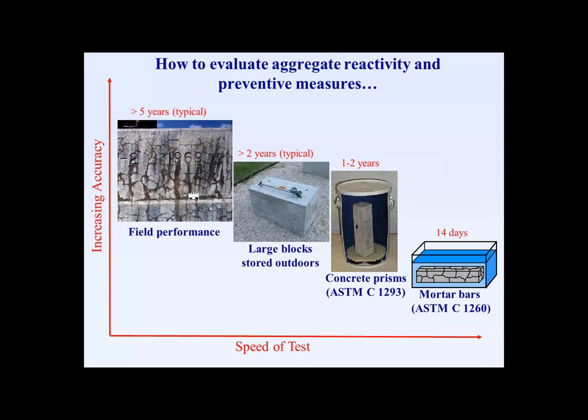To summarize this overall concept, if we were to plot increased accuracy on the y-axis, and speed of the test on the x-axis, things would stack up as you see them here. The field performance of the actual aggregate used in the field is a great indicator of how it might perform in future construction. The problem is you might need 5 years or more in order to use field performance as any index. I'll come back to field performance in the next slide to talk about how we could use it if we tried. Large outdoor blocks are very useful. We've got some great data out of them, but typically we're talking more than a couple of years of test duration and large resources needed for such an endeavor.